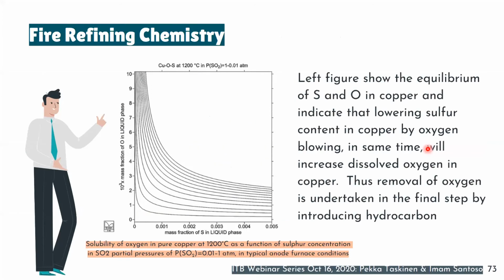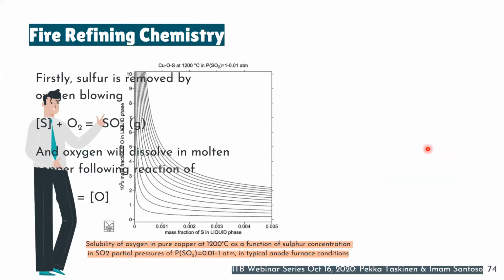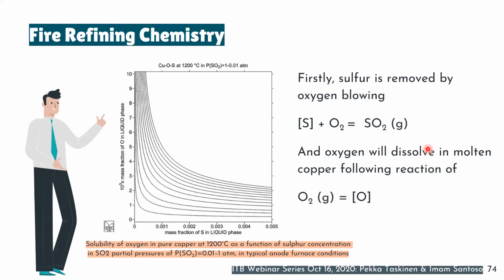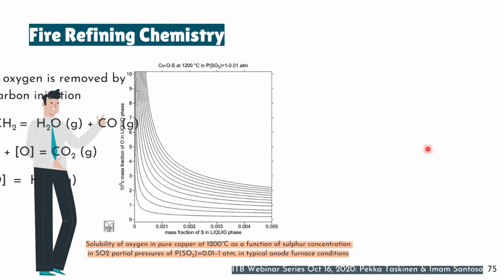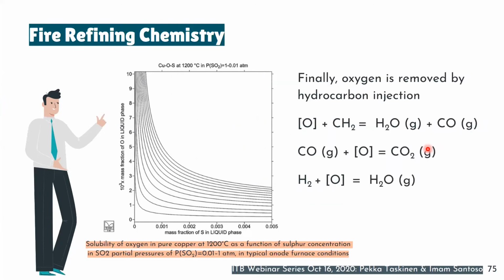And again, this is the same relation. When we have very low sulfur content in the copper, the oxygen will be very high, and thus we need a two-step process. So this is the reaction mainly. Firstly, we remove sulfur with oxygen, and oxygen will be dissolved in the copper, and after that, we remove oxygen with hydrocarbon.